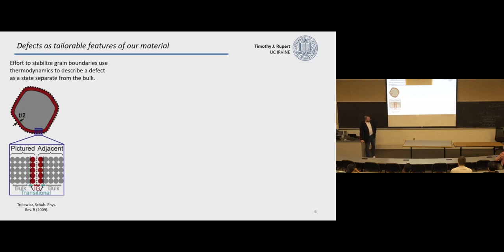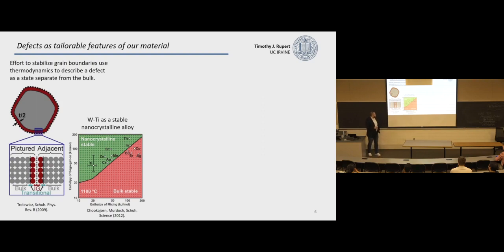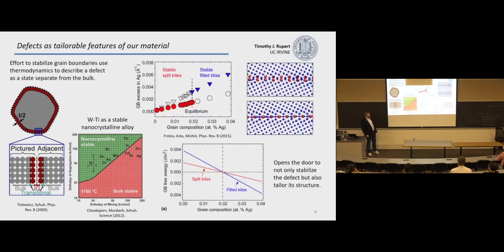Luckily, there's been a lot of work in this area. I'm going to show you an example from work people have been doing to try to stabilize nanocrystalline grains. And a key idea that came up there was, rather than just think of your internal microstructure as details that we don't care about and everything is the bulk, people have been thinking about how you can describe the thermodynamics of inside the crystal and also the grain boundary region as separate entities. And if you do something like this, you can say, if you wanted to stabilize nanocrystalline tungsten, go and understand how you can add titanium and make a stable nanocrystalline structure. In terms of that alloy design, that's kind of nice. It's just thinking about dropping the grain boundary energy.